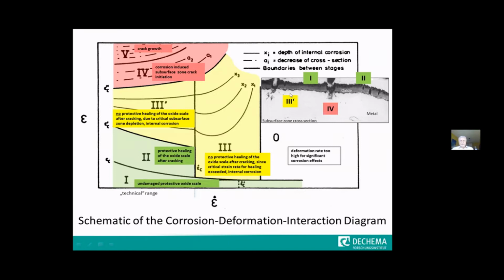As we've seen before in one of the slides, this crack, which usually goes through the whole scale, can heal by oxidation at the bottom of the crack, so it's refilled again and can be completely closed. You can see some features here which remind you of very short cracks, but which are actually healed cracks. In this case, the protective effect is completely restored by the healing process. Again, you need to be below a certain critical strain rate, because otherwise the growth of the oxide would be too slow to close this crack again.